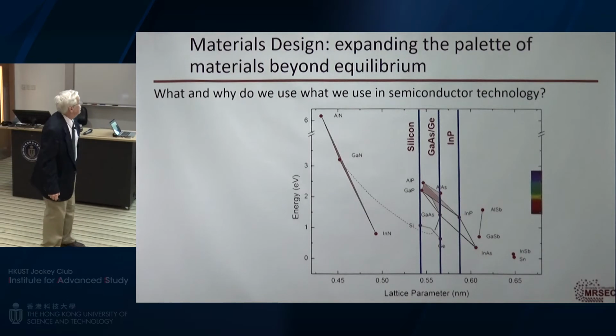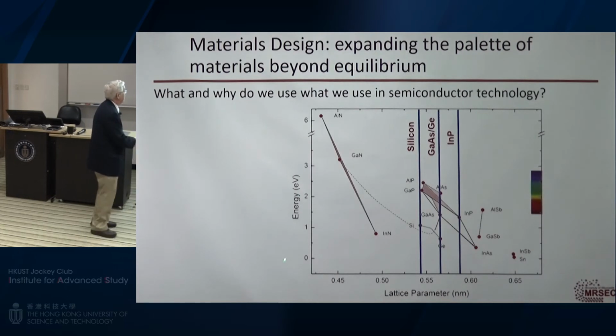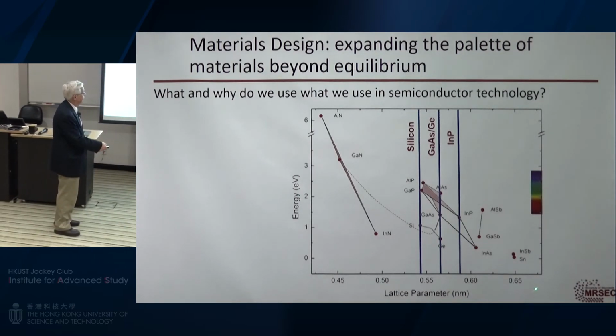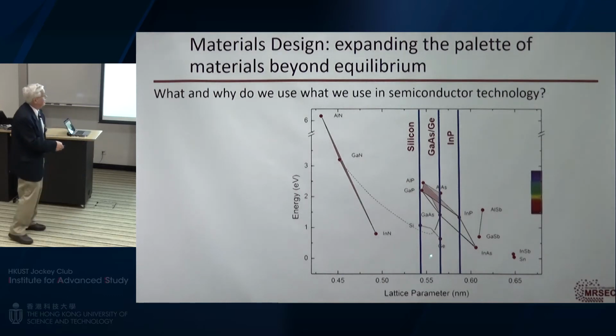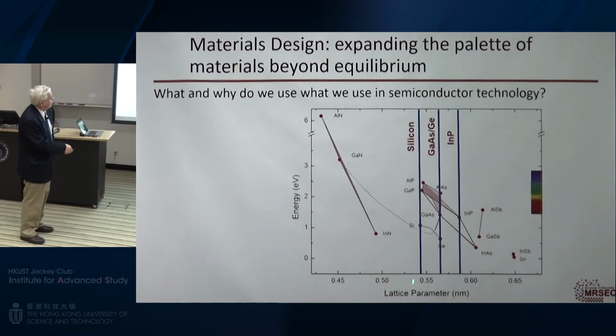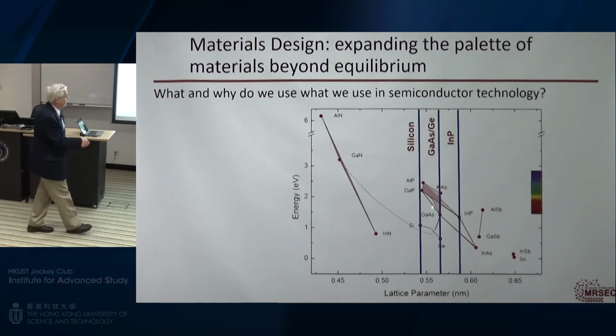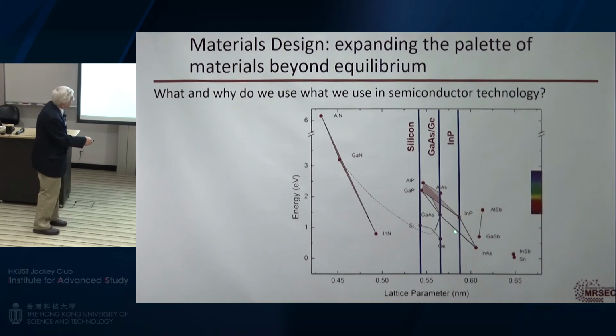So if I look at the semiconductor technology, and this is a typical graph that's used. This is the band gap energy, the characteristic energy of the system, versus the lattice parameter. And these are all the common binary and elemental semiconductors. And these are those bulk crystals that I could grow, and I can use these for epitaxy. So the things that I generally use are those that lie on these lines because they have the same interatomic spacing as the compound that I'm wishing to grow. And so you see these lines here. Anything connecting these lines are things that we've made and are stable. And most of what's inside these shaded areas we use technologically and are stable.